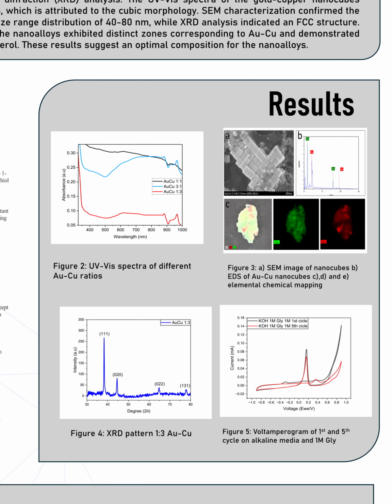In the scanning electron microscope image, panel A displays orderly arranged nanocubes measuring approximately 40 to 80 nanometers. Additionally, smaller spherical nanoparticles are visible on the surface of these cubes, along with a layer of orderly nanocubes beneath them. In the energy dispersive X-ray spectroscopy image, the analysis shows that the gold-copper ratio of the analyzed nanocubes is 1:3. The elemental chemical mapping image indicates that the small spherical nanoparticles are composed of copper.